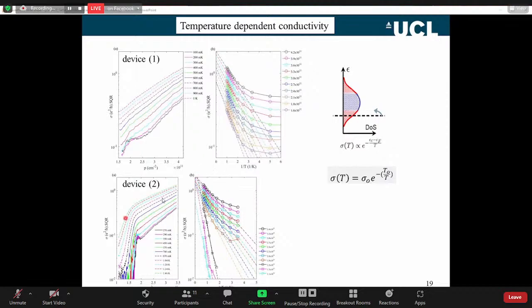When we looked at a second device, number 2, from the same wafer, it has the same structure, it's just a different batch in processing. We were much more careful at monitoring what was going on in the device. So the conductance, this is our device conductance as a function of gate voltage or area density, comes down, turns round, and then it turns up. Same as we reduce the temperature, we get the same features, we get the drop in conductance, we get the slight turn up, then we get the sudden increase in the activation energy, plus this mesoscopic noise.